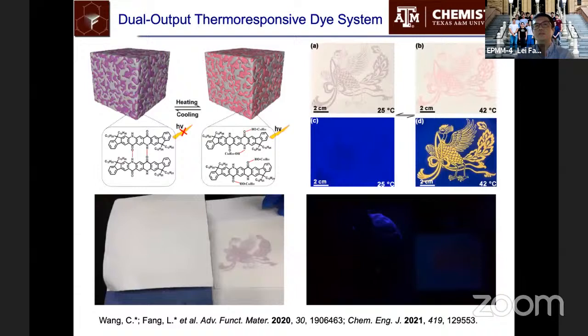So utilizing this, we designed a type of hybrid material. We blended this kind of supramolecular solution into a polymer matrix such as PDMS. Then we print it. It could be made into thin films, or we could print it onto fabrics. Here we show the change of the color by changing the temperature.